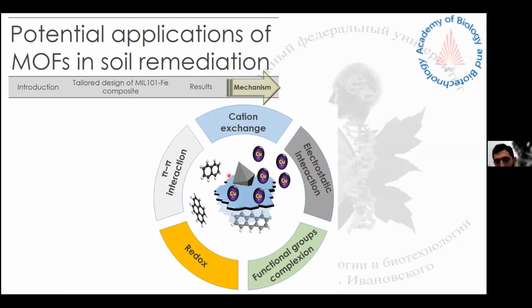And the pi-pi interaction, we can say that only MIL-101 offers in the composite. So once we have this interaction, this benzene ring can be close to the structure, and they can be trapped easily by the composite. And this one, redox, that I want to mention here and highlight, is a very novel mechanism that we got from the composite only. So what is redox? It's based on oxidation and reduction. We couldn't measure, but we see a very low amount of low molecular weight polycyclic aromatic hydrocarbon remaining in the soil. So it means that they haven't leached, but they have been oxidized and degraded, and the benzene ring has been opened up. So we just propose that we can have an advantage of redox reaction as one of the possible mechanisms that we have during this amendment of the metal organic framework with biochar.